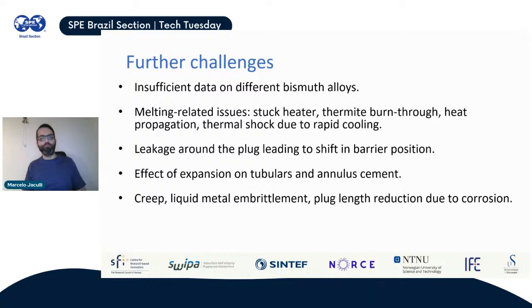And then you have some problems related to the material properties. You have creep behavior, which is relevant for high temperatures. So you might be unable to use a particular alloy in a well whose temperature is closer to the melting point, because that could damage the sealability of the plug. And then there is some threshold temperature that you can use this plug safely. Otherwise, you need a different type of alloy for that particular application. There is a concern about liquid metal embrittlement. This is a phenomenon that happens when you have a solid metal, in the form of the casing steel, and then you have a liquid metal in the form of the molten alloy. There are some known interactions in the literature where some liquid metals can damage solid metals and damage their properties.